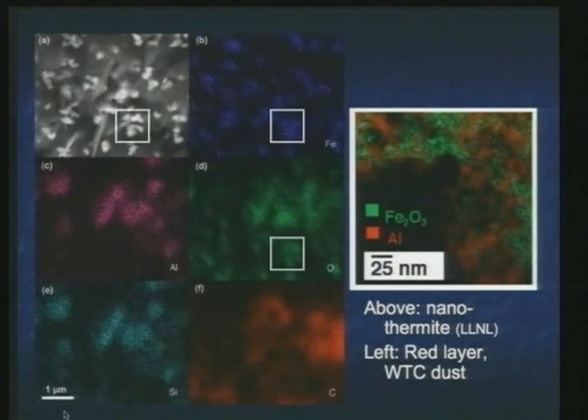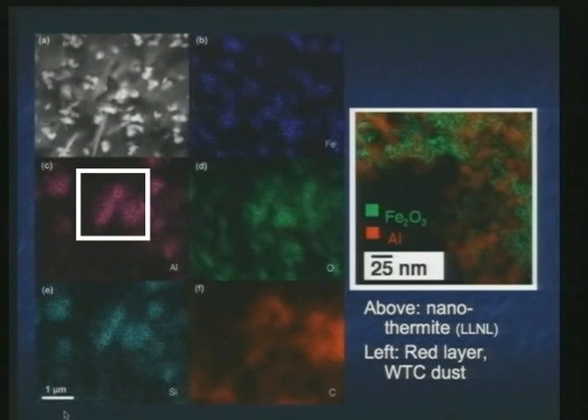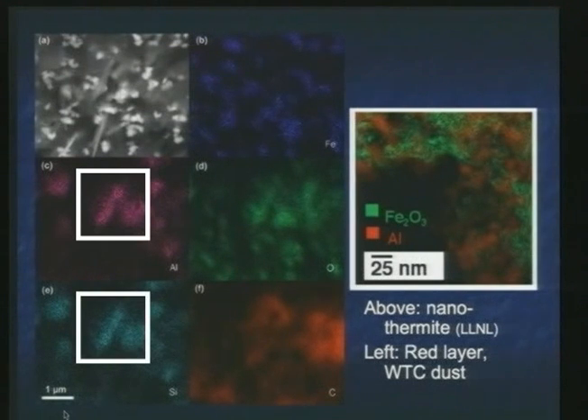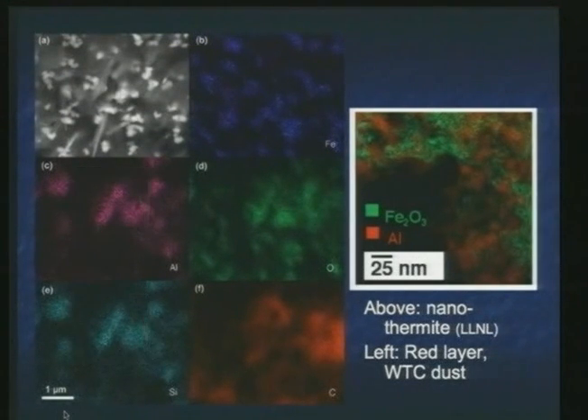And what we see is that we have iron oxide and aluminum, although here you can't tell real clearly whether it's aluminum oxide or not because there's so much silicon associated with the aluminum as this stuff is constructed and engineered. It wasn't until we did the MEK separation that we found the aluminum pulled apart from the silicon oxide and that we're able to nail the presence of metallic aluminum. Again, you can look in the paper. There's another SEM map there. But again, we have this intimate mixing of iron oxide and aluminum and